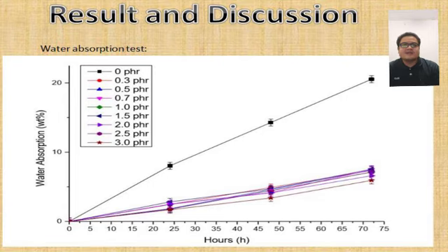This can be related to higher cross-linking between polyurethane chain, resulting higher density of the coating. The water molecules are now harder to diffuse inside the structure of the coating. Thus, the addition of silicon dioxide improves the hydrophobicity of palm oil polyurethane.